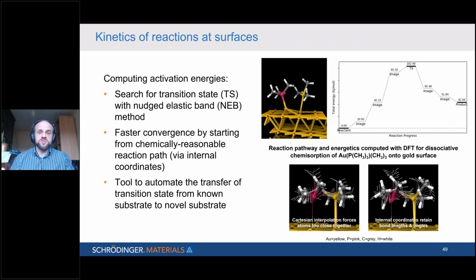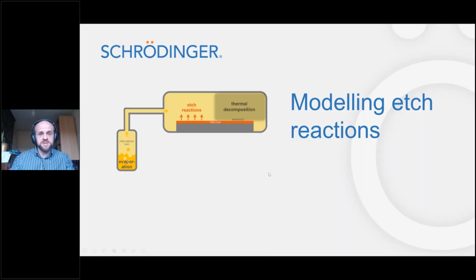Finally, thermodynamics is one thing, but you may also want to know about kinetics. And this is the same precursor showing how it actually dissociates on the surface and what the reaction path for that is. It's an activated process, and we've been computing the activation energy. You can see the sketch there of the calculations that went into determining where the transition state is. It's at an energy of 102.9 kilojoules per mole. And of course, the activation energy feeds into the kinetics and an understanding of the temperature dependence of the process. So having good tools for computing that is also important. And I'm just showing in the sketch below how we can efficiently find these kinds of steps along the reaction profile, the reaction pathway. So as well as deposition, we can also look at etch.